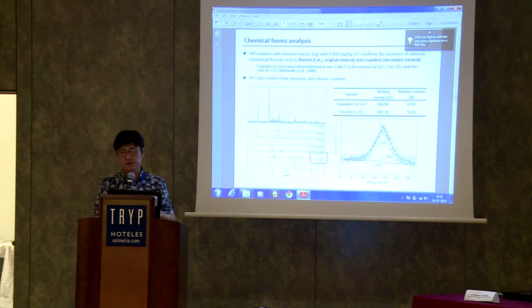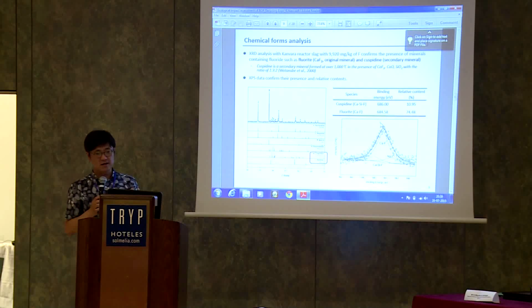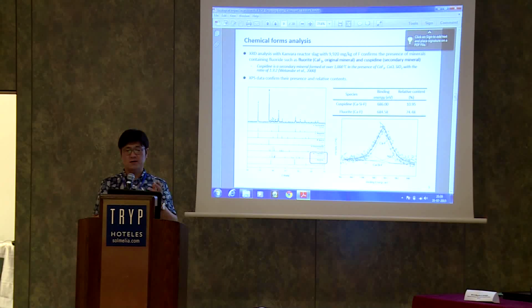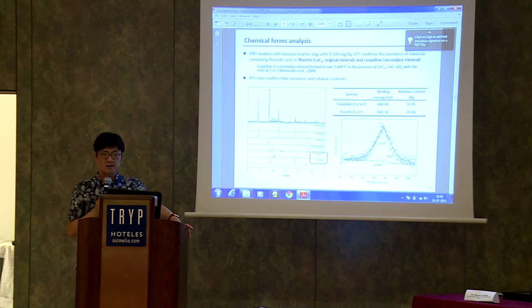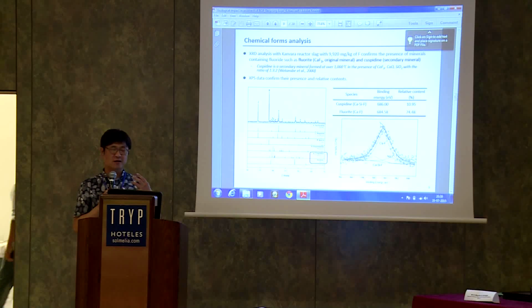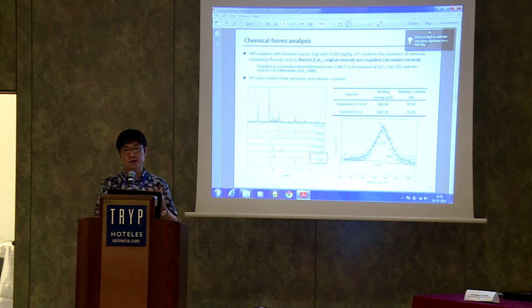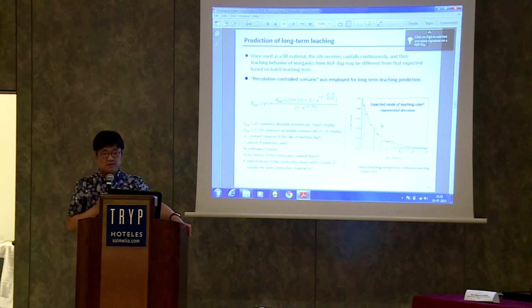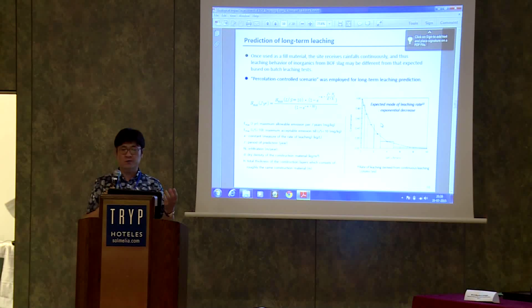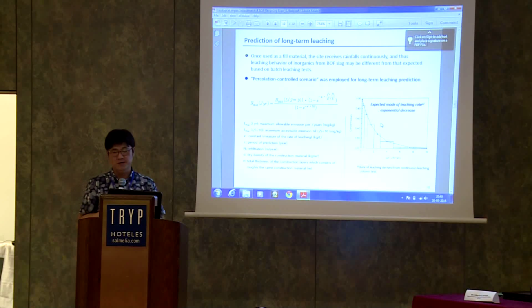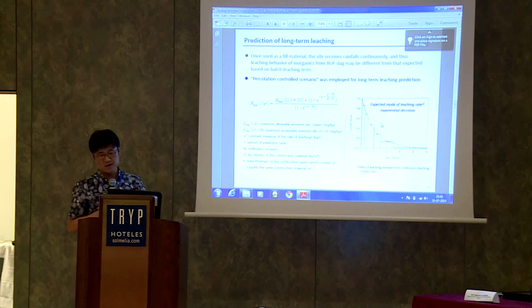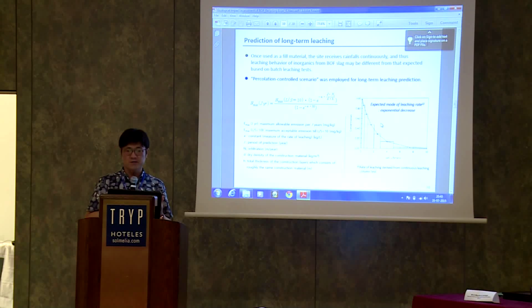And up to these results, we can see that the fluorine or fluoride or zinc in slag, BOF slag, does not have some adverse effect on the environment in terms of regulation. But once the materials are used as a fill material in soil, the site receives rainfalls continuously for a long time, and thus leaching behaviors may change. So we need to predict, or look at, the long-term effect of such leaching behavior.